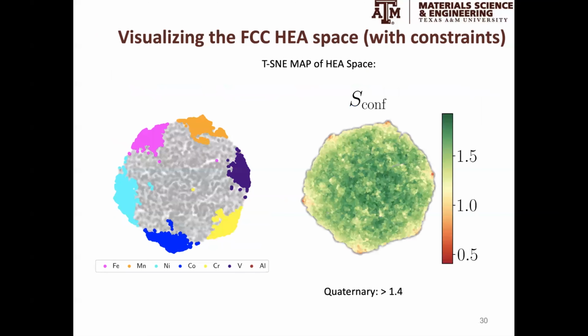The first thing we do is try to map the configurational entropy. Of course, this is not the actual configurational entropy of a system, but rather the maximum attainable configurational entropy for a given composition, just using the entropy of an ideal solution. A quaternary system corresponds to entropies of 1.4.